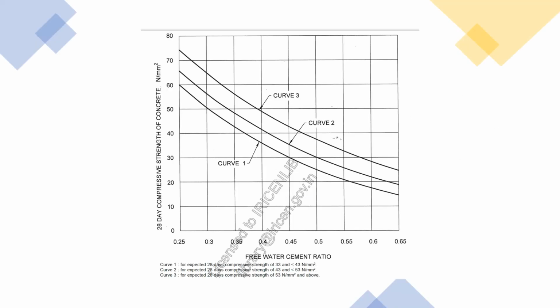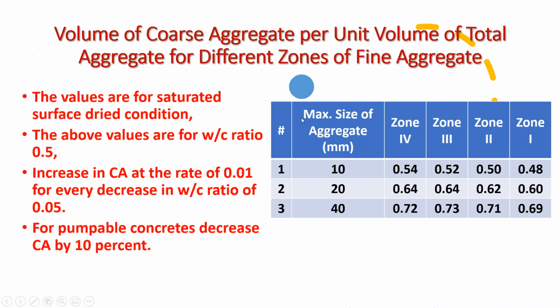And these are the curves, water cement ratio versus the 28 days strength curves. This is for 33 grade OPC, 43 grade OPC, then 53 grade OPC. But one thing, there is a small change between the 2009 version and the 2019 version. In some of the zones, these values have been changed. The solid volume of the coarse aggregate has been changed a little bit in some of the cases. So this is the revised table.